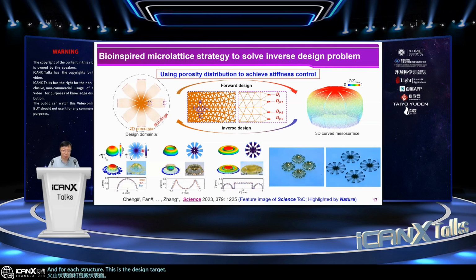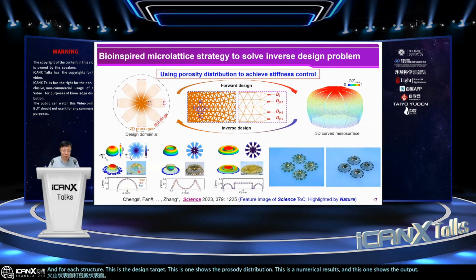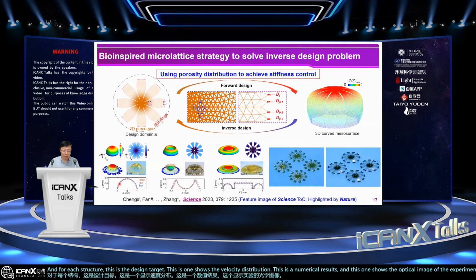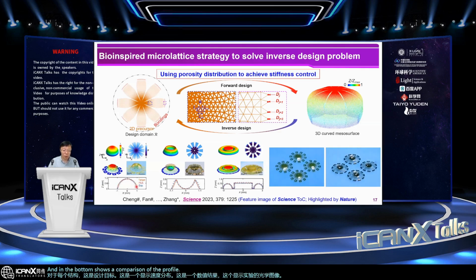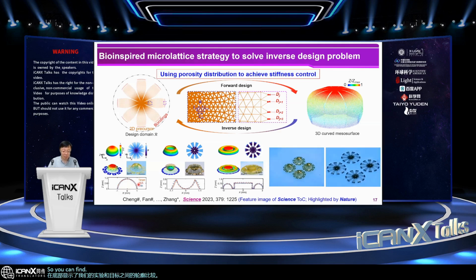This one shows the porosity distribution. This is the numerical results. And this one shows the optical image of experimental result. And in the bottom shows the comparison of the profile between our experiments and the target. So you can find good agreements between our target and our experimental results for all of these three different surfaces.